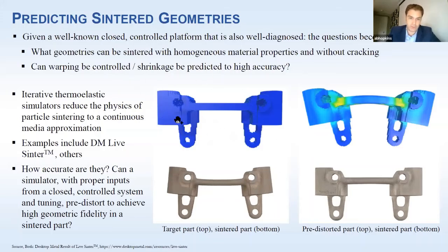You can address it through these thermoelastic models, which there are many. Live Sinter is one of them. Live Sinter will iterate and pre-distort the part. So you'll print this. Then when you put it in the sintering oven, it still distorts, but it comes out as this. So a far less distorted part. The ability to do this is important for binder jetting because if you can do it, it can be applicable to larger and larger parts, making this a viable technology in the hundreds of thousands of tons, not just in the maybe low thousands. I don't know what the other comparison is.